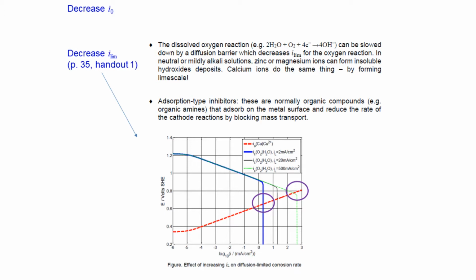Finally, if we don't like the sound of that kind of inhibitor because it might create too thick scales, we can talk about adsorption type inhibitors. These are normally organic compounds, often fairly unpleasantly toxic ones, kinds of organic amines, which adsorb onto a metal surface and create a mass transport barrier that slows down the rate of the cathode reaction by blocking mass transport of the oxidizing agent to the metal surface.